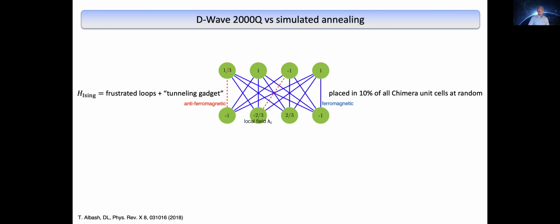The details don't matter too much. The values in the circles are local fields. The blue lines are ferromagnetic couplings. The red lines are anti-ferromagnetic couplings. So it turns out that this gadget, we studied it in this paper, it turns out it exhibits tunneling, which, for reasons that I don't have time to get into, is an important aspect of this gadget for this problem.